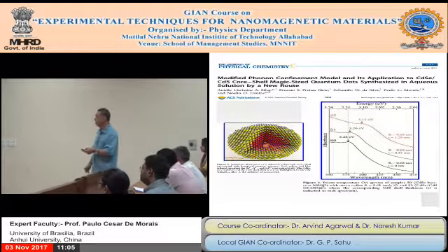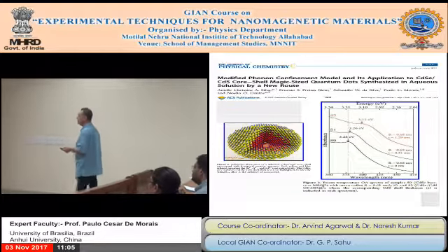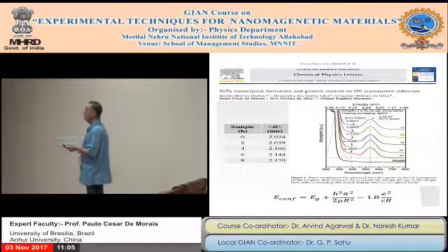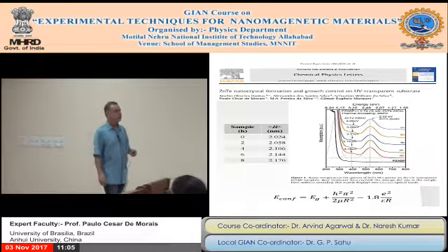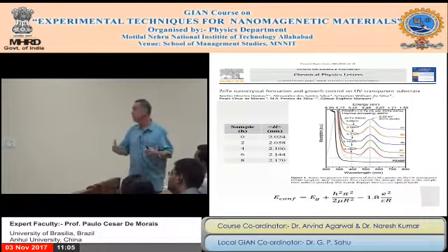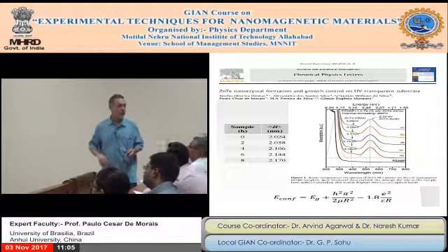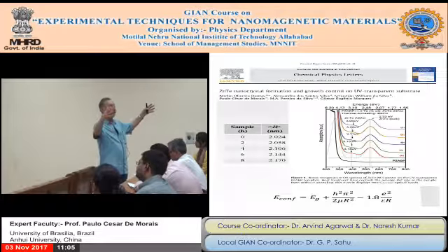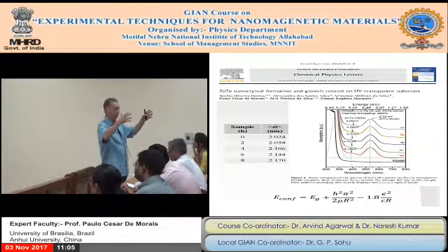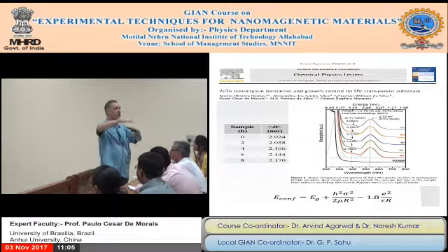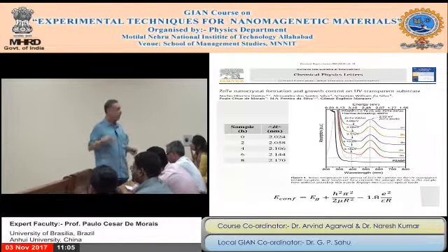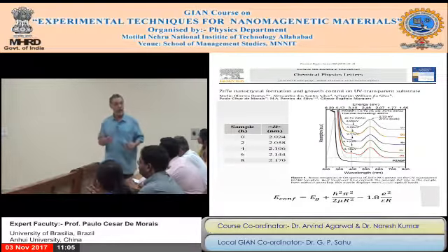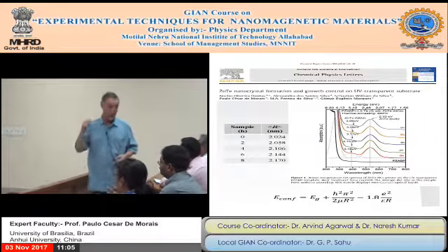Well, finally, this one is a different system, zinc telluride, also a typical semiconductor. Again, they were fabricated changing the size of the nanoparticle. And it comes from the same system. So you have a quantum dot, and then you have quantum confinement. If you change the size, the energy levels just move up and down. And you can fit the data using an equation like this. Not a very complicated equation. This is an approximation.